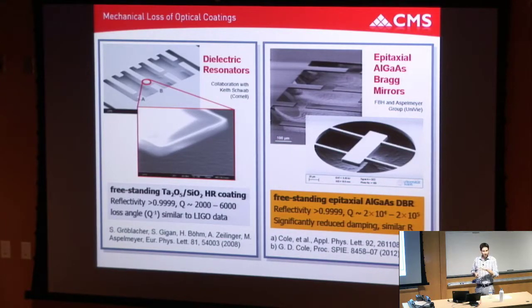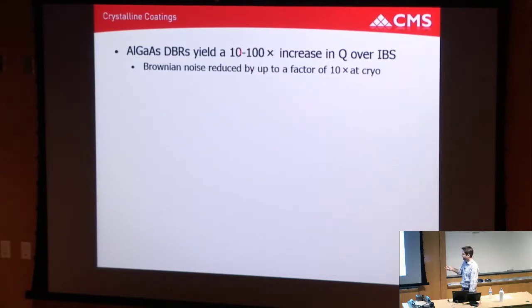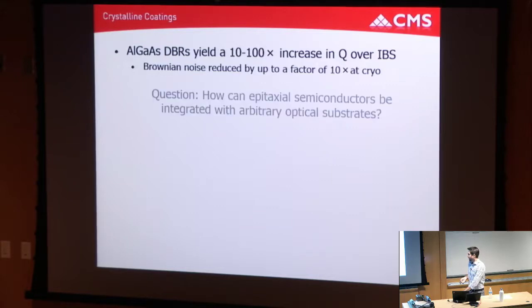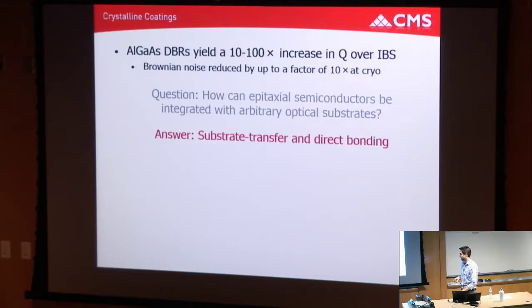It seemed interesting. The two difficult aspects were they needed curved substrates, and they wanted to deliver me a piece of fused silica and have me do MBE on that surface. It doesn't work. I need a crystalline seed to do the growth. So we know we get this high increase in mechanical quality factor, so in principle we can make low Brownian noise optics, but we can't do direct deposition. So the idea is, how do we integrate these two things together? I had a background in high power amplifier and laser structures where we did direct bonding between disparate semiconductor materials. So I knew how to do bonding, but the curvature scared me a little bit.